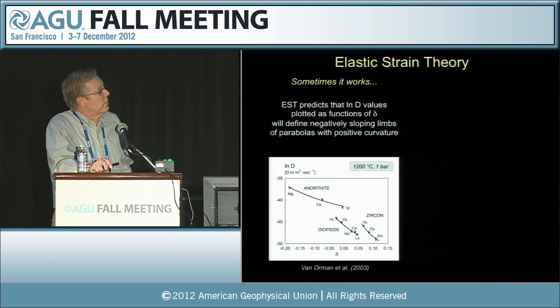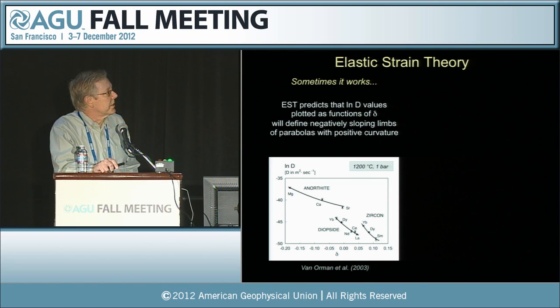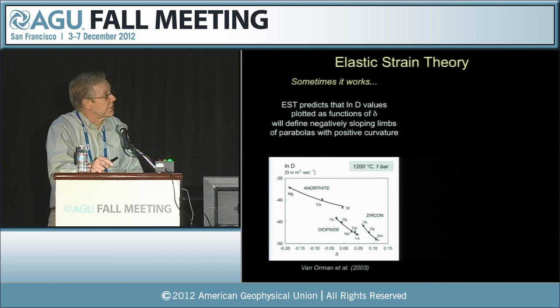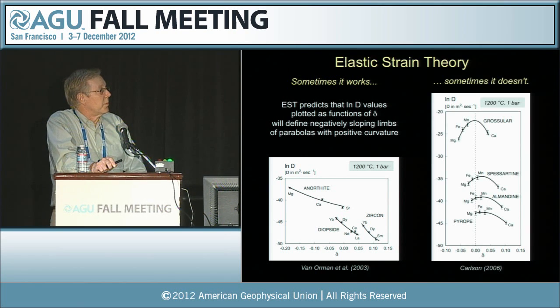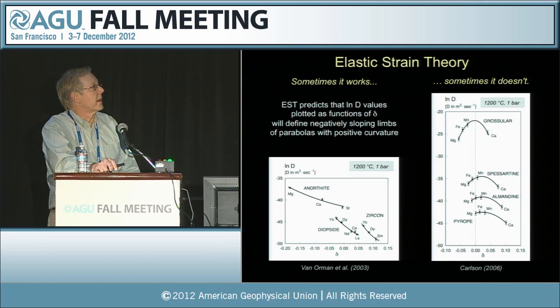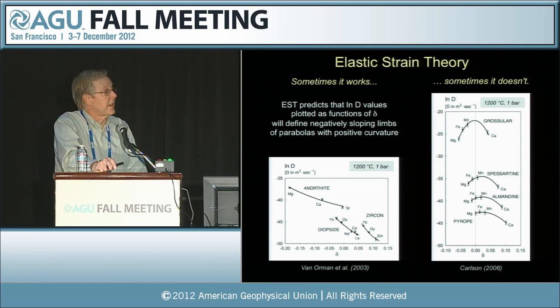Well, sometimes this theory works. It's quantitative. It predicts that the logarithm of the diffusivities, when plotted against this misfit parameter, should define negatively sloping limbs on parabolas that have positive curvature. And these data from Van Orman et al. actually fit that sort of relationship. But here are those garnet data that we saw a moment ago, plotted at exactly the same scale. And of course, the differences here are quite dramatic. Now, they're so dramatic, in fact, that some critics have claimed that this has to be just an artifact of a bogus model.